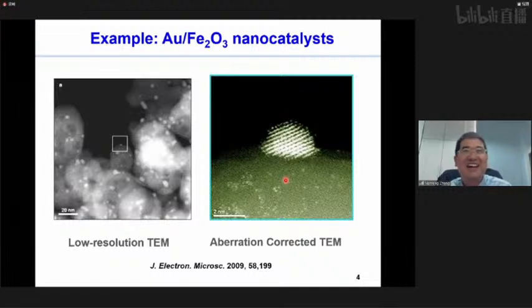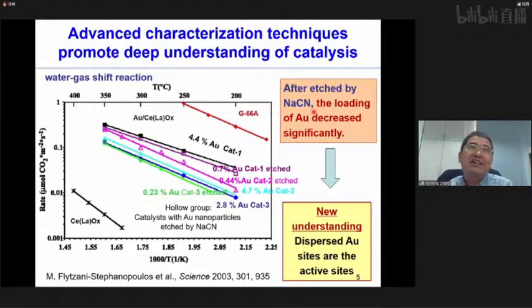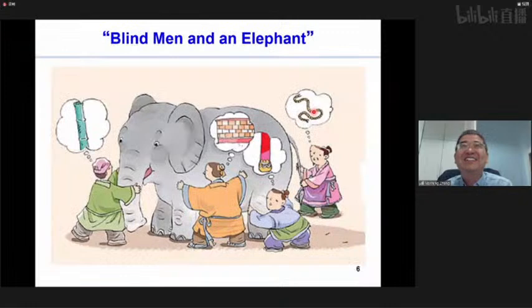But what is really funny is that we can use sodium cyanide to etch out those gold nanoparticles. Which means that if we use conventional TEM, we will not be able to see anything, right? Nothing there, I mean the gold particles. But if we use this sample after etching for the water gas shift reaction, we observe quite similar activity. So what kind of feeling do you have? Do we really believe what we see? No, right? This is really like the blind men and the elephant. We only see part of this catalyst.